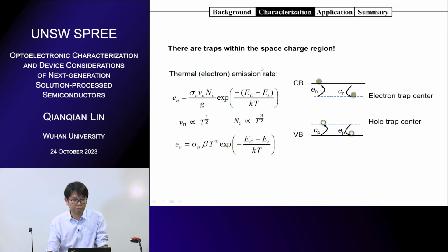What will happen if the material has traps? It depends on time, because the carriers can be trapped and re-emitted. The emission rate is highly dependent on the depth of the trap states and also the temperature. If you have a higher temperature, carriers have more energy to escape from the trap states. So we have a temperature-dependent emission rate; the velocity is also dependent on temperature, and the density is also dependent on temperature. Finally, we get a temperature-dependent emission rate.